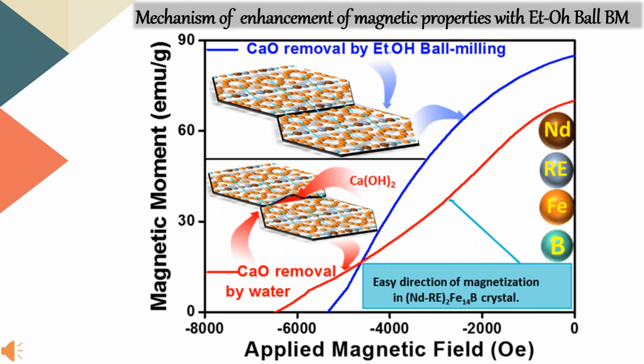Calcium oxide produced during the reduction diffusion process is not good for the magnetic properties of the final product. So 2 different methods were used to remove the calcium oxide. One was washing the product with water, and the second was washing the product by the ethanol ball milling process. In the ethanol ball milling process, the particles were separated more efficiently because of the ball milling, and the crystallinity of the product was also improved because of the vigorous ball milling. Overall the calcium quantity was also reduced in the final product, as shown in the supporting information of our paper. The BH max of the ethanol ball milled product was almost doubled compared to the water wash product, for 2 reasons: the removal of the calcium hydroxide, and the improvement of the crystalline structure. The details of both mechanisms are shown in our paper.